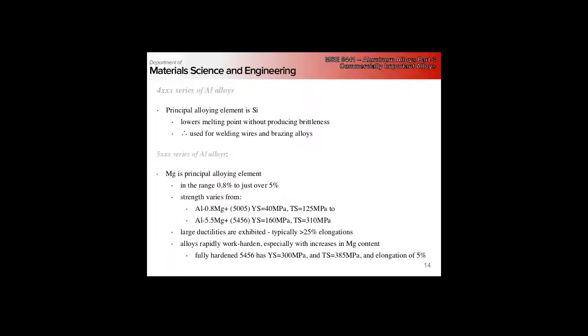5000 series, alloyed with magnesium. Remember, we don't get age hardening out of the magnesium, but these are typically used in the solid solution strengthened state because of the low degree of hardening and the very low solvus temperature of GP zones in magnesium.